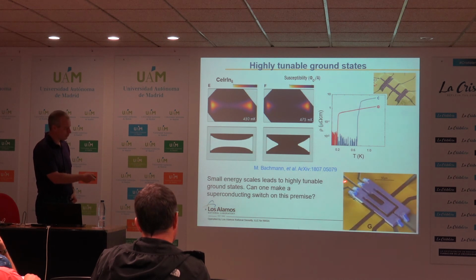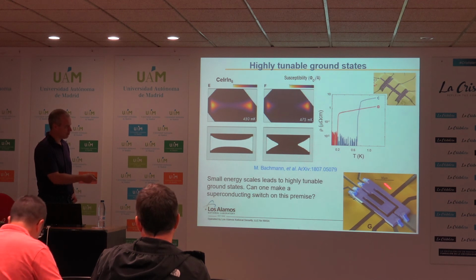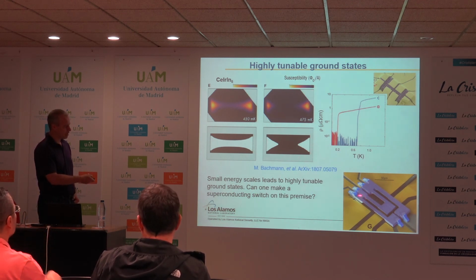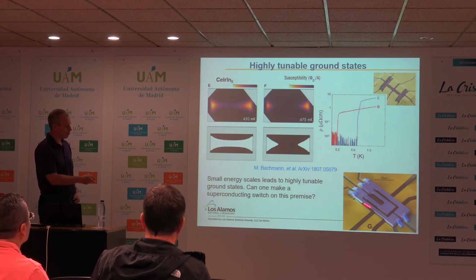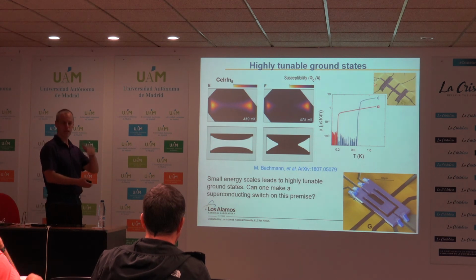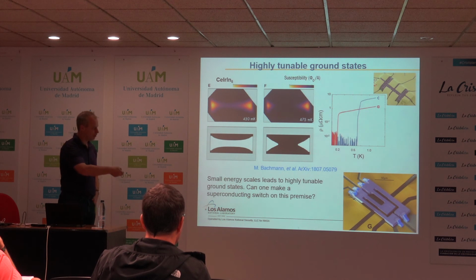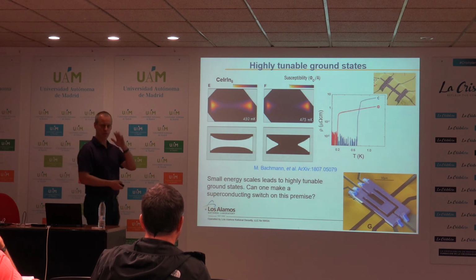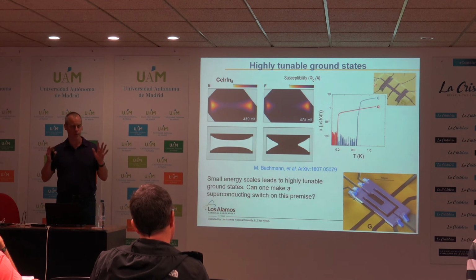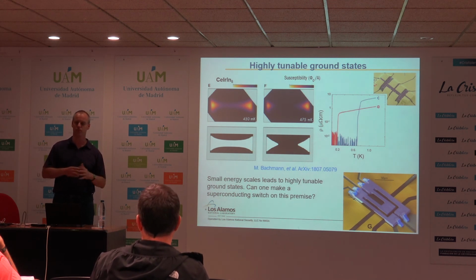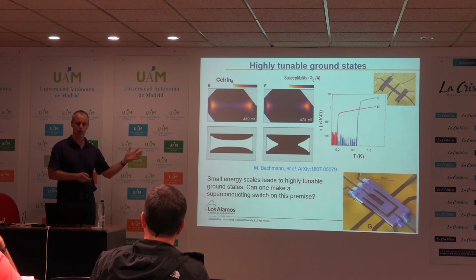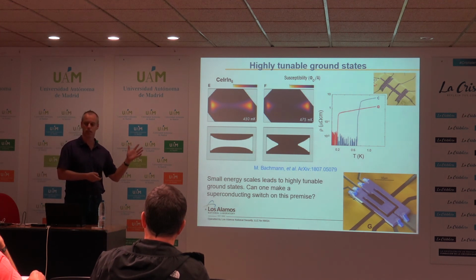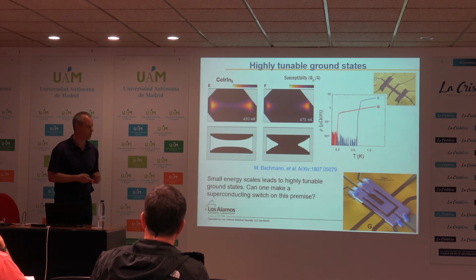And in fact, Philip Moll is even making, this is a picture of cadmium arsenide, but you can envision a similar type of structure where the purple is CeIrIn5, you apply a gate voltage below the system, and you could bend your sample up and down. The thing which we are going to try and do is tune the superconductivity on and off just with this gate voltage. So in general, you might imagine, okay, heavy fermion superconductors, this is not the place for applications, but in fact the tunability of the ground states means that for quantum technologies, this might be an interesting route, and this is something that we're pursuing.